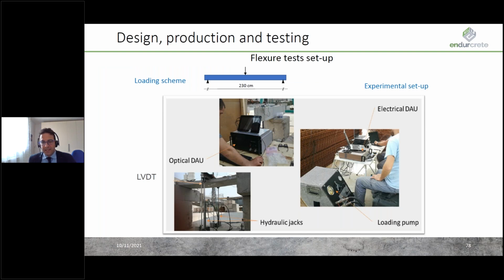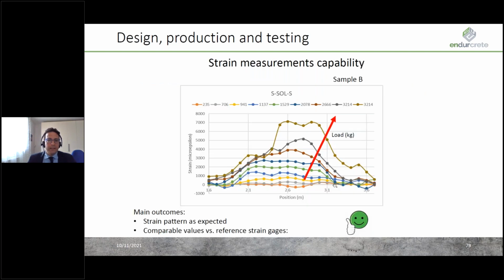The panels were then tested in 3-point bending test. Here you can see some details of the setup, and here the main results, namely the strain profile along the panel at increasing load. We can comment that the strain pattern shape is as we expected it, and also that the strain values we measured are comparable with those obtained by reference electrical strain gauges.